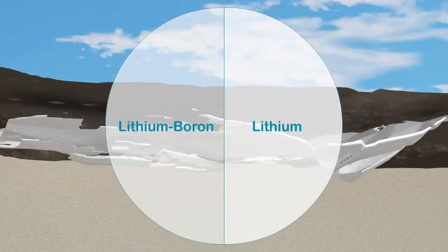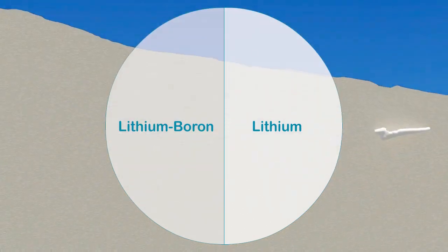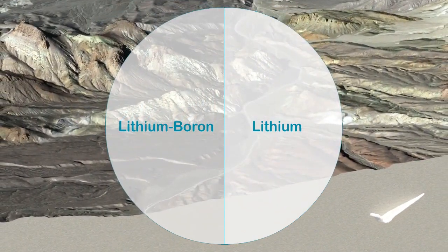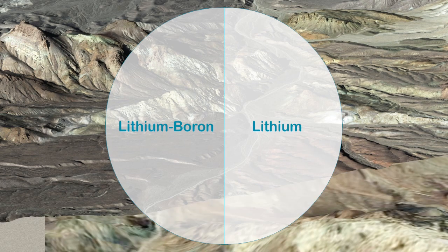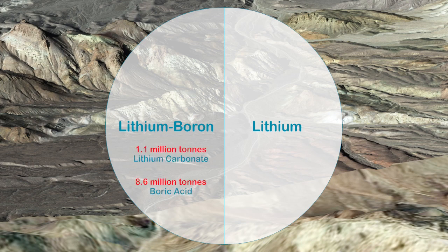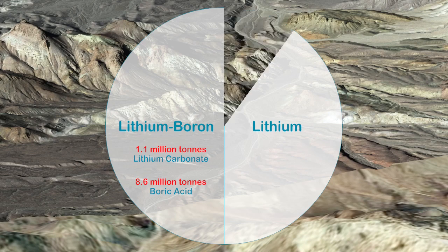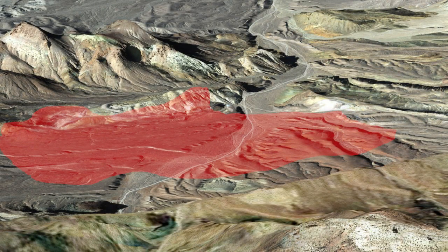This can be divided into two distinct parts: a lithium-boron portion, in which the rock is dominated by the boron mineral searlesite, and a lithium-only portion in which the rock is dominated by clay and contains no boron. The higher-value lithium-boron portion is estimated to contain 1.1 million tons of lithium carbonate and 8.6 million tons of boric acid. It is the lithium-boron portion depicted here that is the focus for the company's proposed development. The lower-value lithium-only clay-rich mineralization will be stockpiled for possible future processing if and when economic processing technologies are developed.